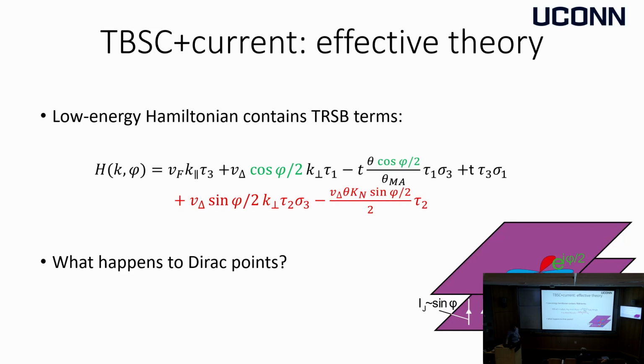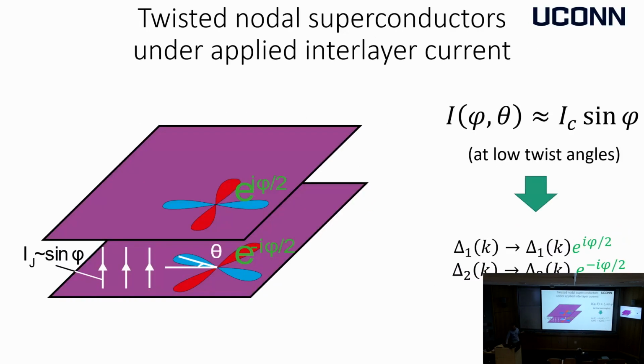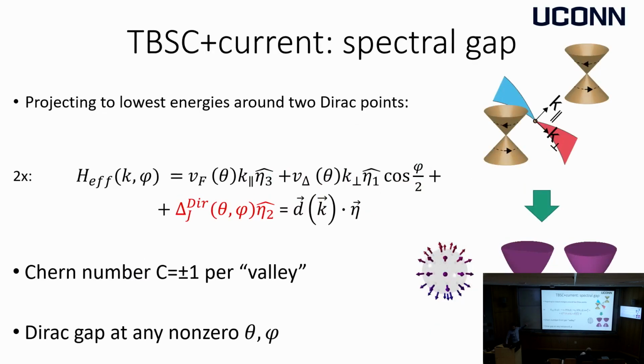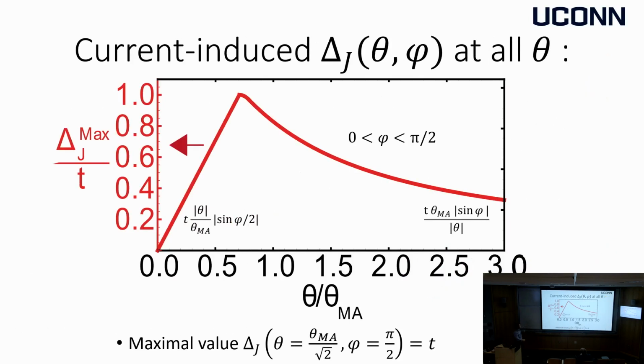Now there will actually be a contactless alternative in a few slides too. Okay, returning to this problem. What I'm saying is that you can generate a phase difference by hand in the system, and that phase difference opens a gap at the Dirac points, which is non-zero at any twist angle. By sweeping the phase difference from 0 to pi half, the maximum you can get, in the Josephson junction by applying current, you can see that the gap grows with increasing twist angle. It becomes of the order of the interlayer tunneling at around the magic angle, not exactly at the magic angle, and then it goes down as basically 1 over twist angle.